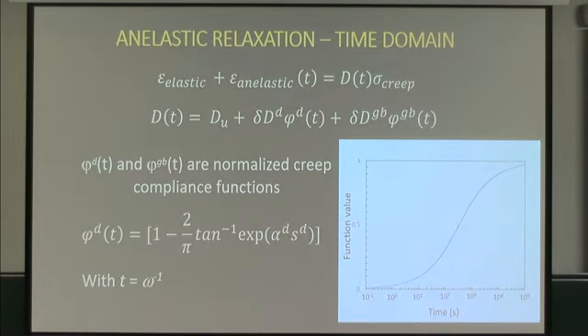You can take a look at this in the time domain. So we typically express this time dependence in terms of what's called a normalized creep compliance function. It goes from 0 to 1, and it gets scaled by our friend here, this delta D for dislocations. There's one also for the grain boundaries. Again, that's about an order of magnitude stronger than that guy. They have different activation energies and slightly different peak width parameters.